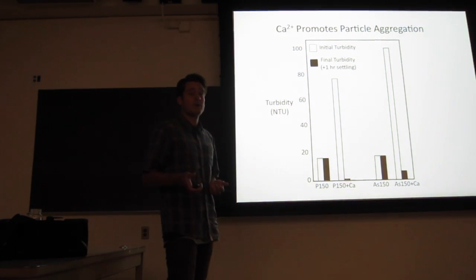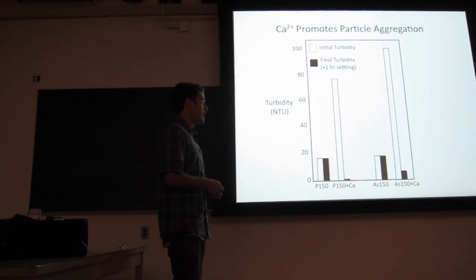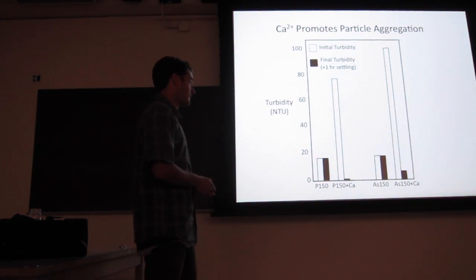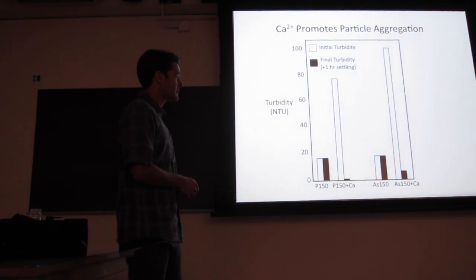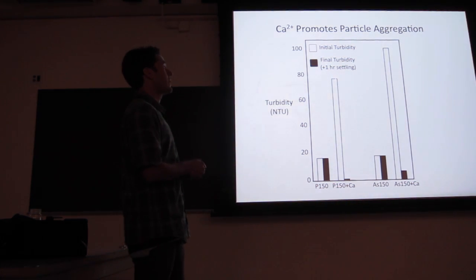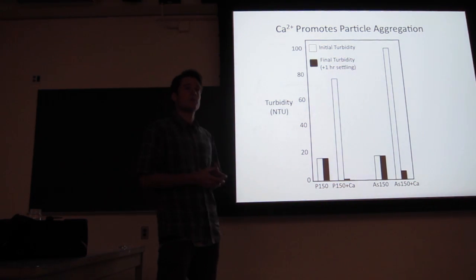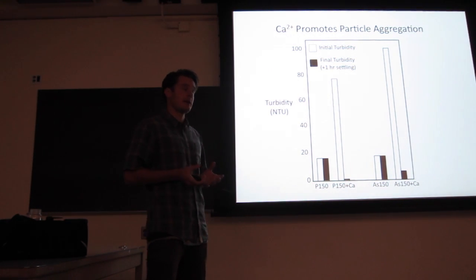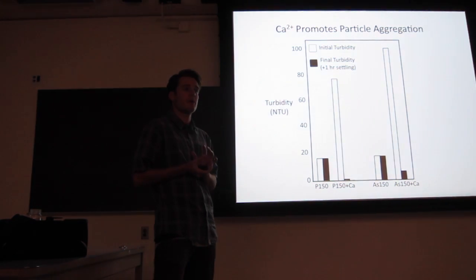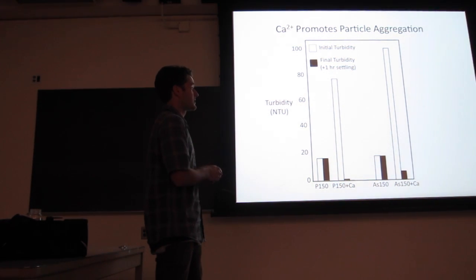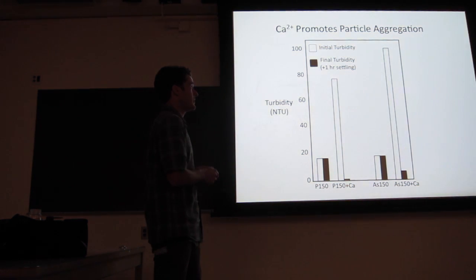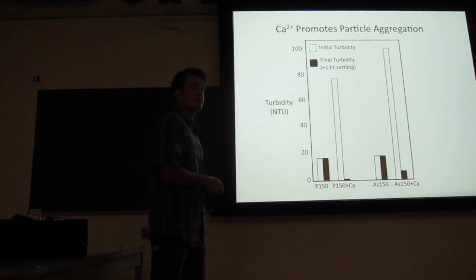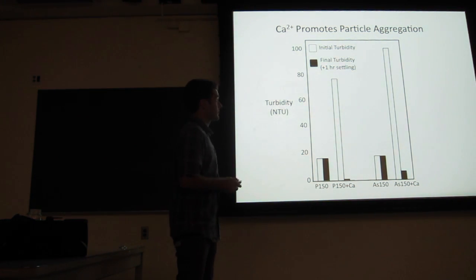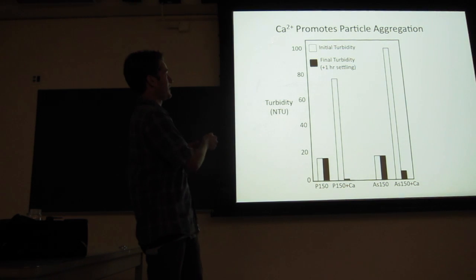And in the field right now, we use alum, but I'll be talking a little bit about that at the very end of the talk. So in the presence of calcium, on the other hand, you generate a suspension with much higher initial turbidity, and that's because calcium aggregates these particles. And these particles then settle really quickly. So the initial turbidity is higher, but the final turbidity is lower. So calcium promotes particle aggregation.